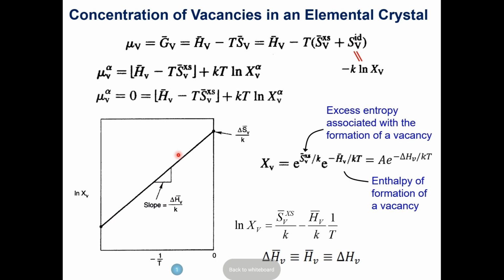To prove how good the straight line is, you need more data, at least one more. The slope will give you the delta H. And if you're interested in the entropic term, you can calculate that too, so you get both the entropic and enthalpic terms. But people are mostly interested in the enthalpic term, because that tells you what temperature you have to take the sample to.